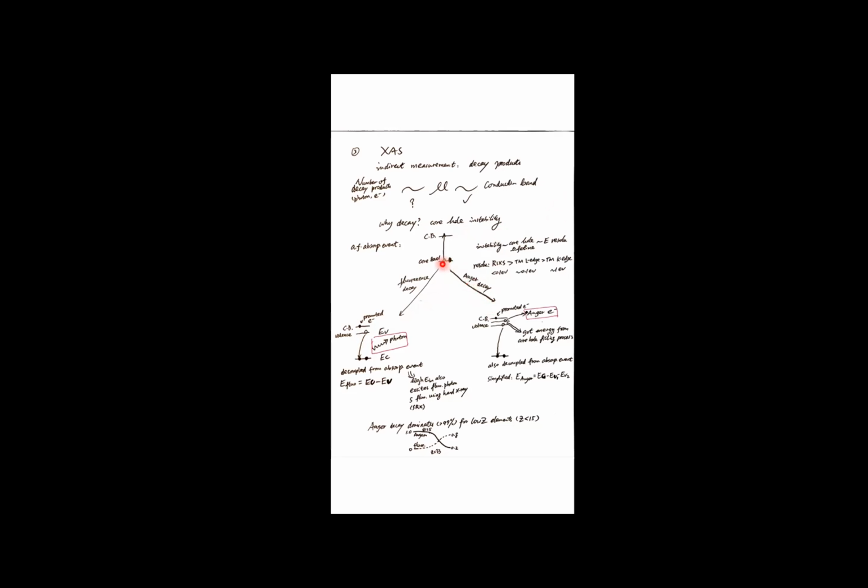What that means is, whenever we have core holes, we have the core hole instability. Then we have the decay channel, and we have the fluorescence decay. So we'll still have fluorescence from the sulfur sample, right? So we can do fluorescence at 5 keV for sulfur, even though the absorption energy is not correct. But we do have outgoing photons. And because we can calculate the energy of the outgoing photons, it's basically the energy difference between these two, right?